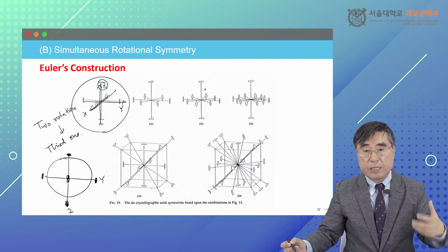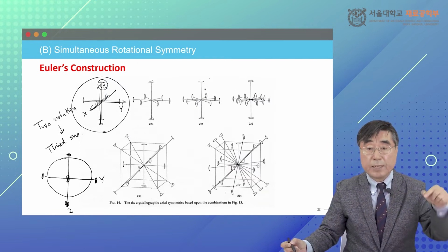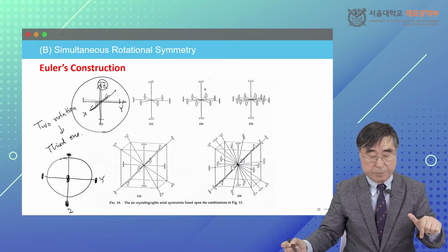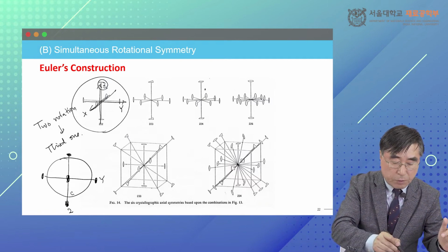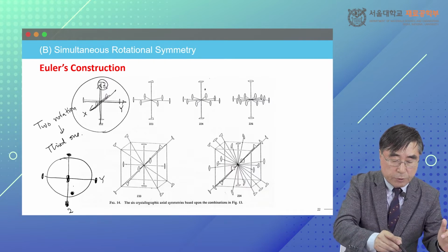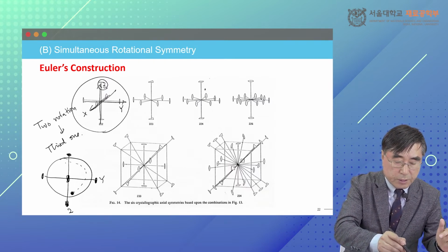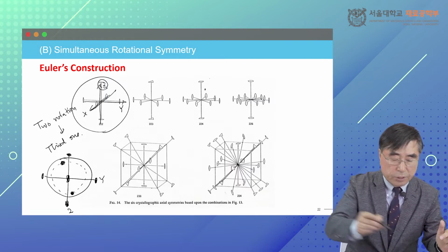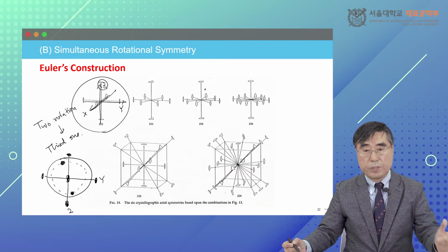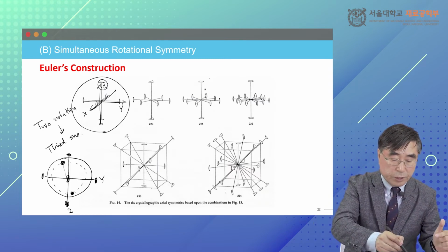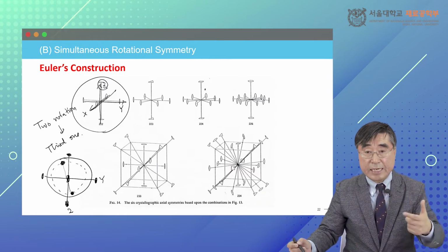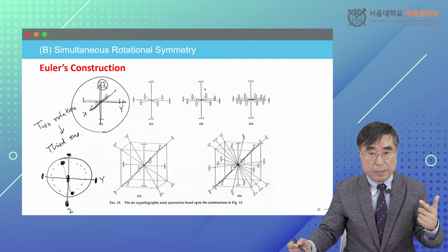So these are the symmetry elements of 2, 2, 2 in stereographic projection. Now if I have one pole here and rotate it about the Z-axis by a twofold rotation operation, then on the Wulff net you draw small circles, and the pole should go there, a 180-degree rotation operation. That's the Z-axis operation.